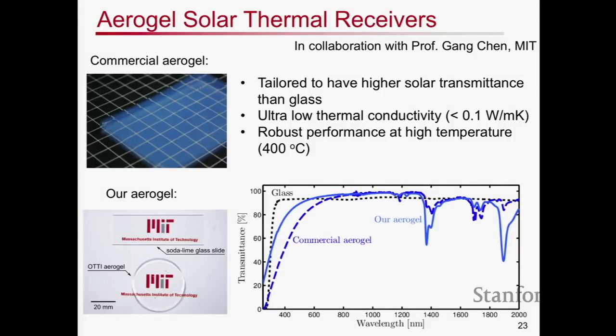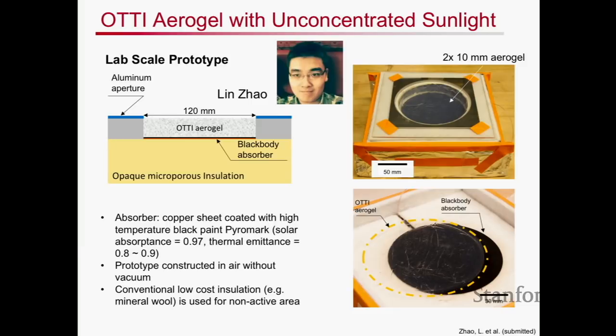And meanwhile, what we've been able to do is still maintain the ultra-low thermal conductivity, less than about 0.1 watt per meter Kelvin, and demonstrated that they can be robust on the order of about 400 degrees Celsius, which is kind of the target we've been focused on such that we can drive a steam cycle. Okay?